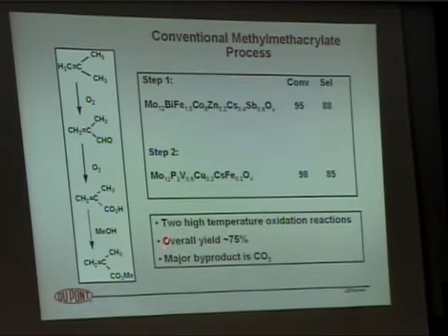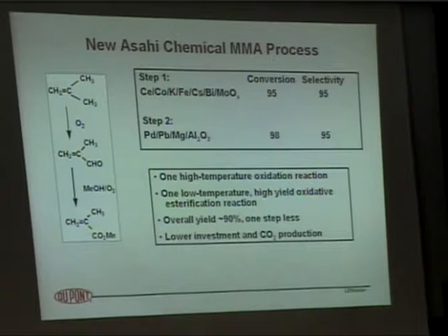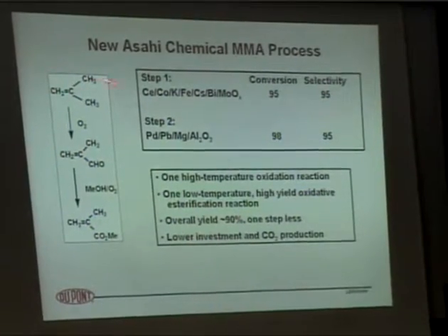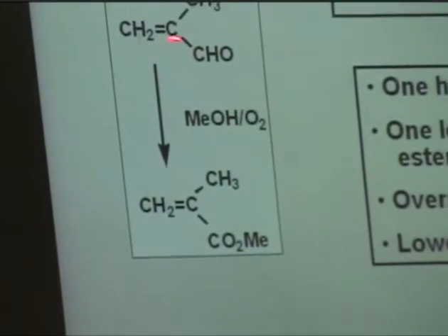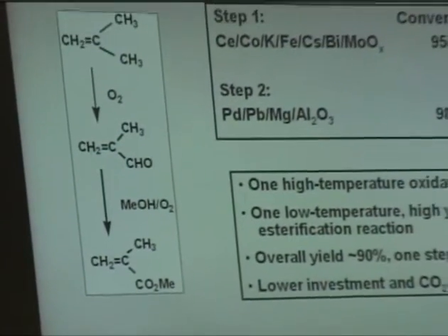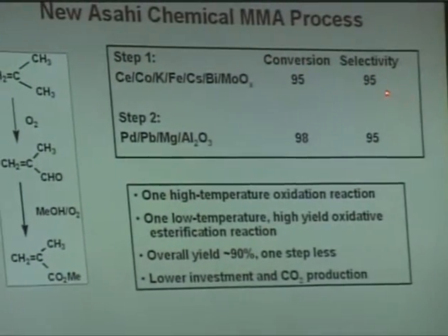Then you've got an acid catalyzed esterification. So you've got a three-step process, two high investment, high energy, relatively non-selective processes to make the methacrylic acid and then the esterification. Well, Asahi Chemical came up with a twist on this that allows them to do this whole process in two steps. So they take isobutylene, oxidize it to methacrolein. They have a catalyst that they've patented, very high conversion, very high selectivity.